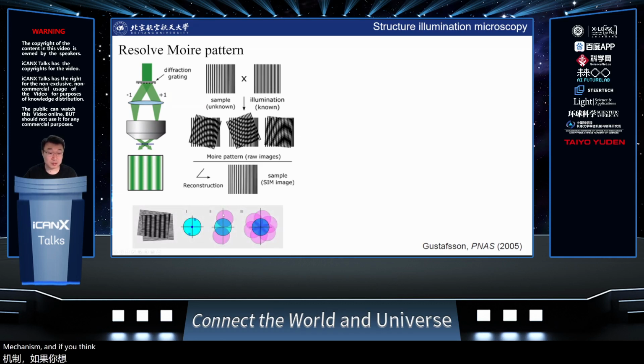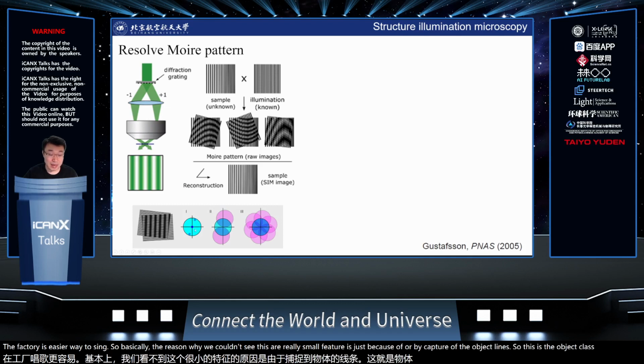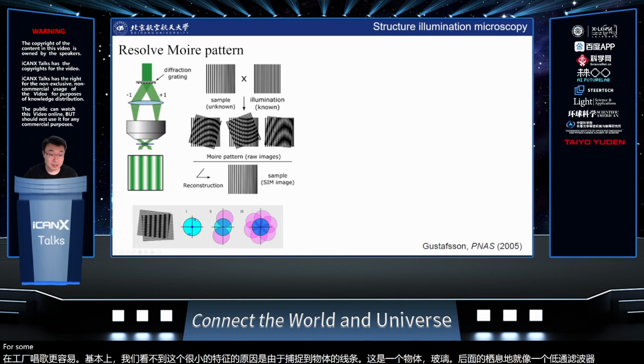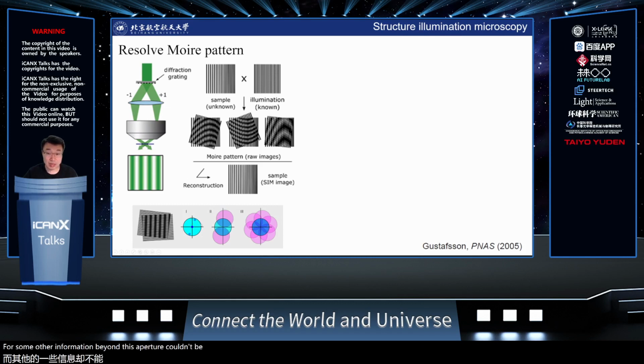If you think from the Fourier domain, it's an easier way to think. The reason we couldn't see these really small features is the back aperture of the objective lens. The back aperture is just like a low-pass filter. Information beyond this aperture couldn't be transferred out. If you put your illumination in some pattern, it's like you are shifting the center in K space. And if you resolve this pattern again, you can have information beyond this limit because you shifted the center of K space. By solving, you need 3 phases and also 3 directions to solve the different patterns, and then putting them together through the inverse Fourier transform, you can have much better resolution.